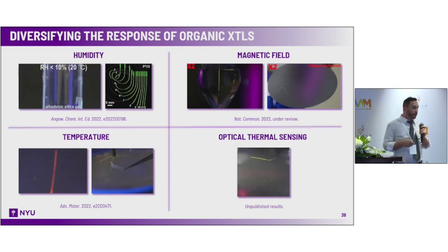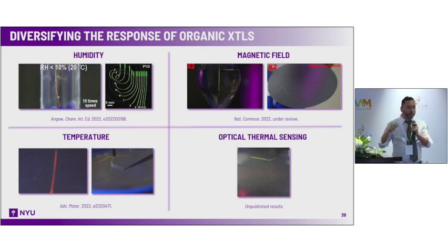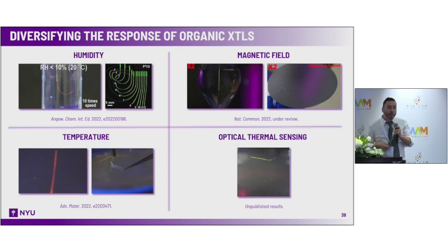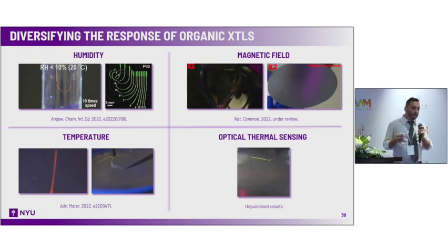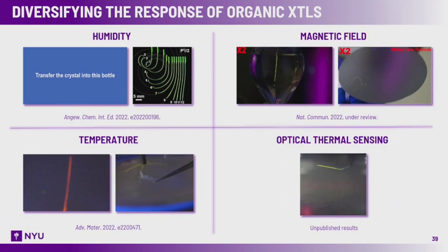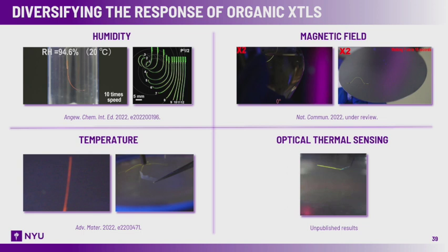So not only humidity, we can also use other stimuli. So we can use magnetic fields. If you have a crystal which is coated with a polymer and we use magnetic nanoparticles on one side, this gives you the opportunity to control the bending or deformation in a medium other than air, so in water, as is shown here on the top right, but also to make some small soft robots where you can control basically the motion of the crystal along surfaces. So now we have accomplished spatial and temporal control of the deformation without these depending on the intrinsic property of the crystal. Now they depend only on how we manipulate the magnet around the crystal.